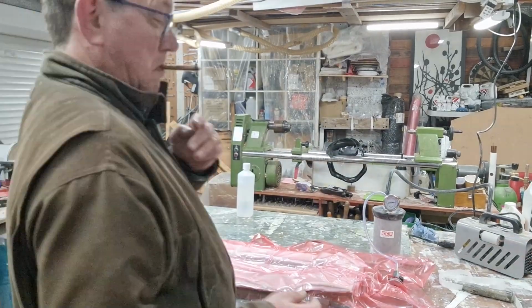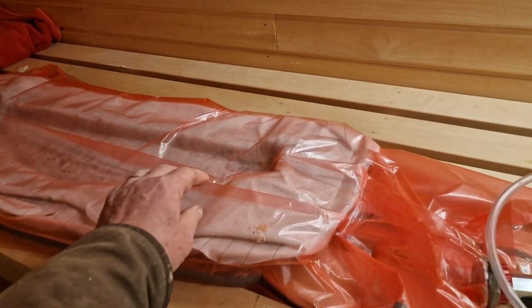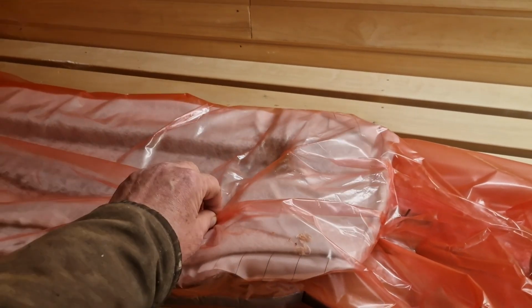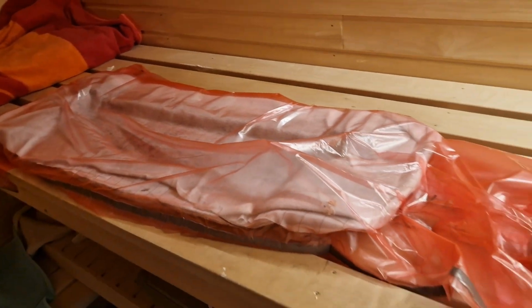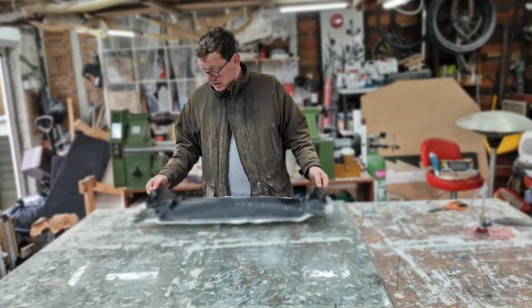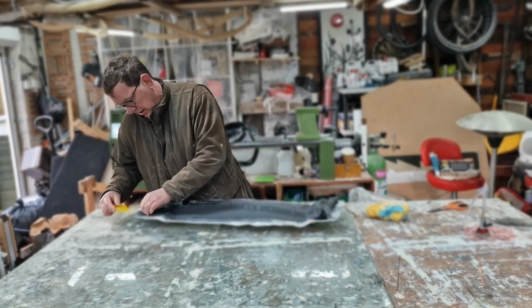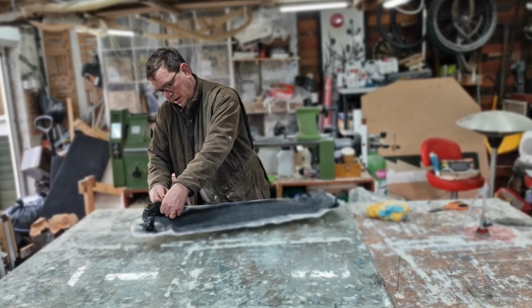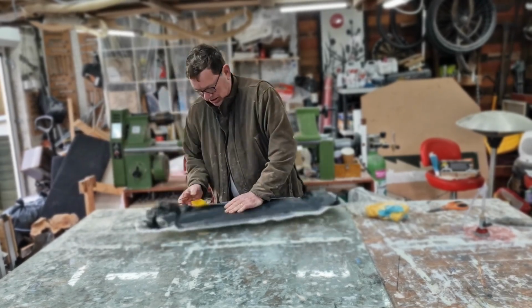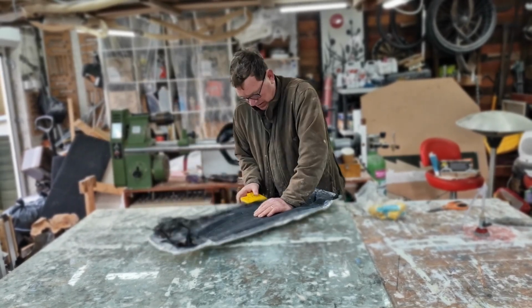This has obviously been drying in here overnight, and what do you know? My vacuum bag's leaked. Here we go for the big reveal. Does the peel ply just pull out? Yes, it does. Will the carbon fibre just pop from the mould? Not exactly. It's not too bad, actually. It took me about 15 minutes.